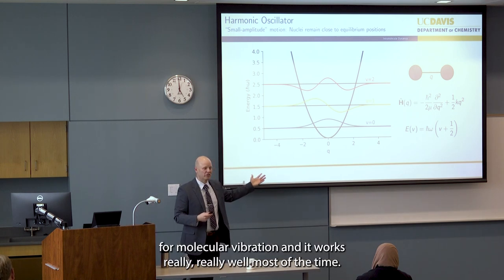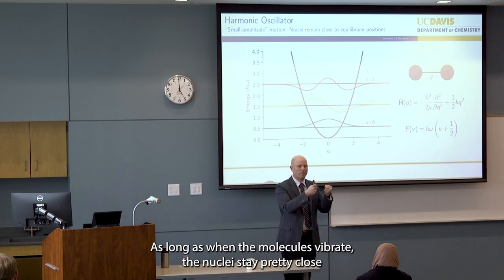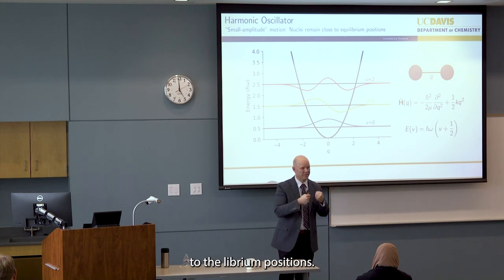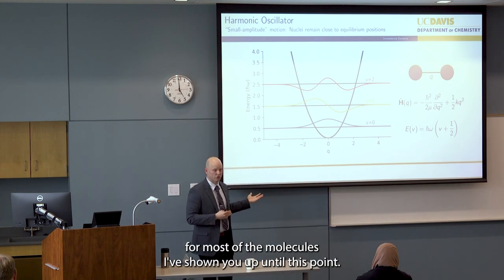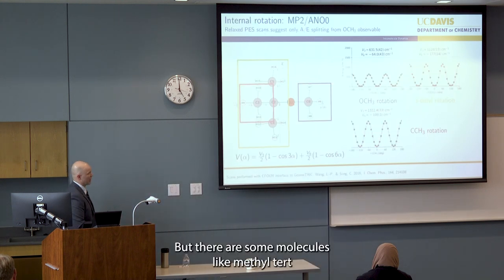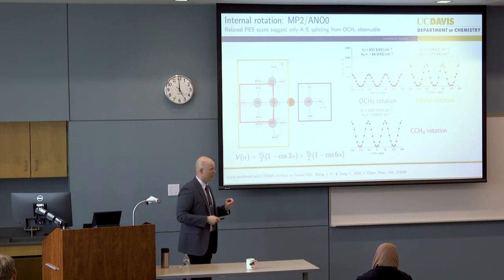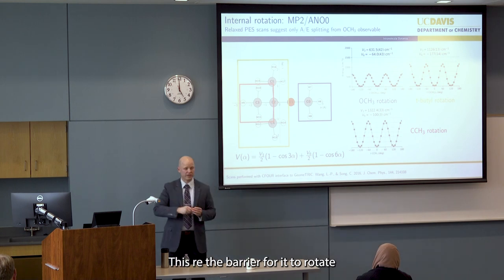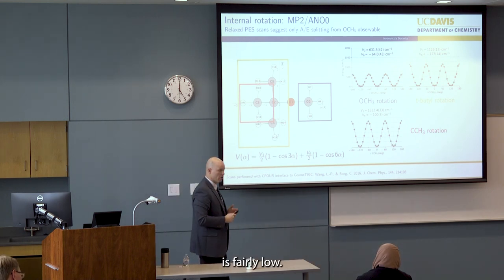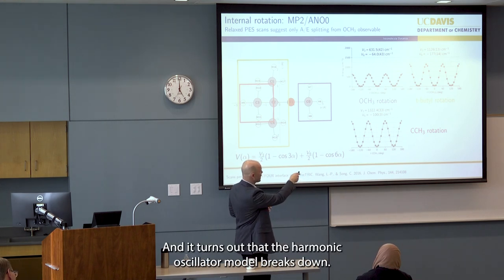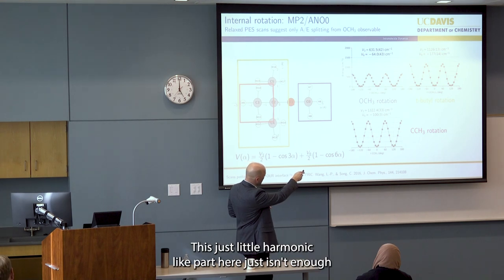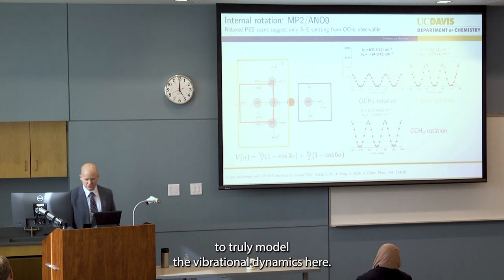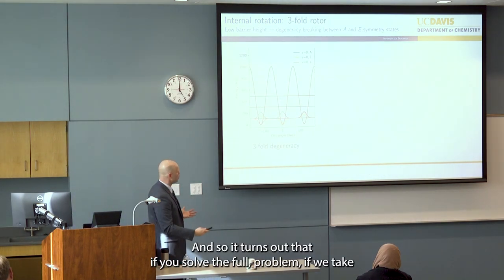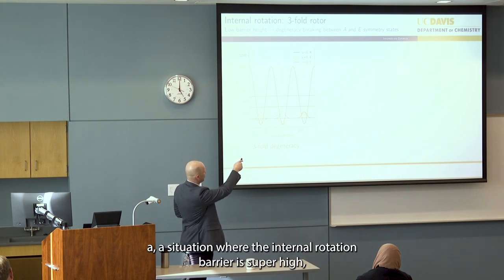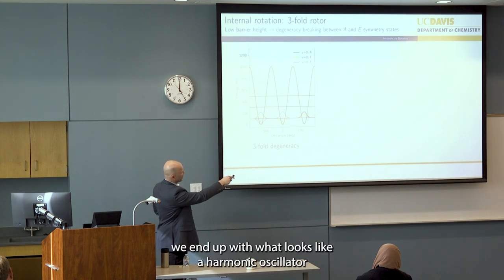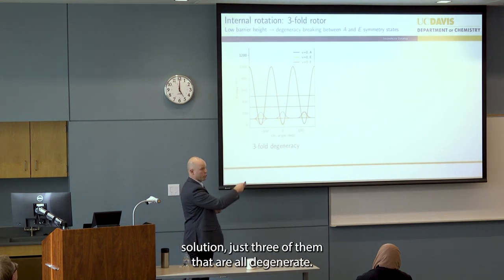This is the model for molecular vibration, and it works really, really well most of the time, as long as when the molecules vibrate, the nuclei stay pretty close to their equilibrium positions. And that has been the case for most of the molecules I've shown you up until this point. But there are some molecules, like methyl tert-butyl ether, where that approximation doesn't hold. In methyl tert-butyl ether, this terminal methyl group over here, this OCH3, the barrier for it to rotate is fairly low. And it turns out that the harmonic oscillator model breaks down. This little harmonic-like part here just isn't enough to truly model the vibrational dynamics here. And so it turns out that if you solve the full problem, if we take a situation where the internal rotation barrier is super high, we end up with what looks like a harmonic oscillator solution, just three of them that are all degenerate.